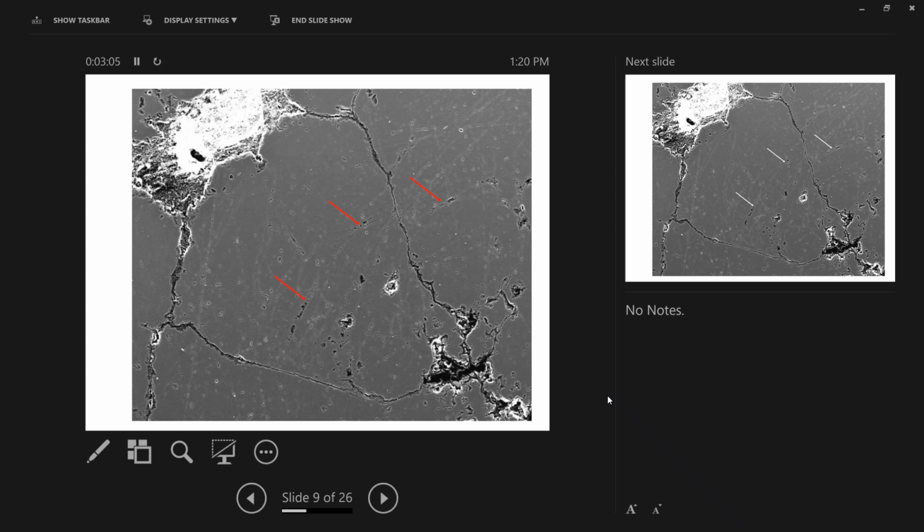So they will throw a raster of points, say 100, 200, 400, depending on an image, and they will literally point count which one of them falls into pore space, which one of them falls into solid space, micropore space, whatever other interpretation you need. That's called point counting. And they will record that result, often in a spreadsheet.